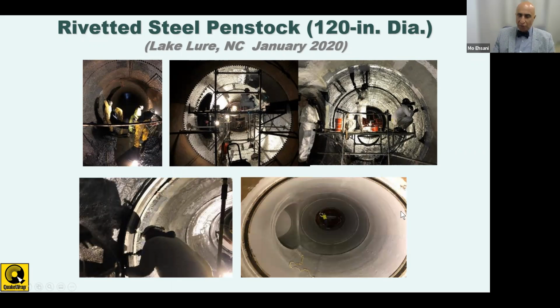Another thing to mention to you here is that when you put a liner like this over a length of these pipes, at the upstream and downstream point of the termination points, we want to make sure that water does not get behind that liner and cause a separation of the whole liner from the pipe. And this can be achieved by using what in our industry is called Weco seal, or it's basically a compression ring that you put on as you see, these workers are installing that here. So you put that over the end of the FRP and then apply tension to it to tighten it against the surface of the pipe.